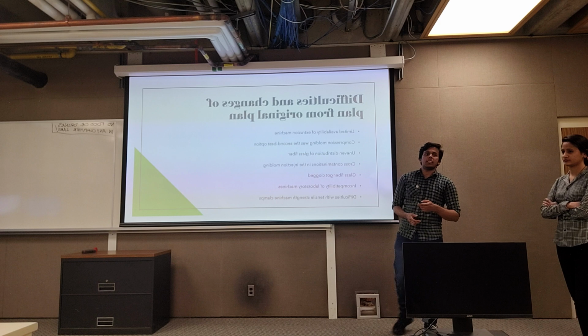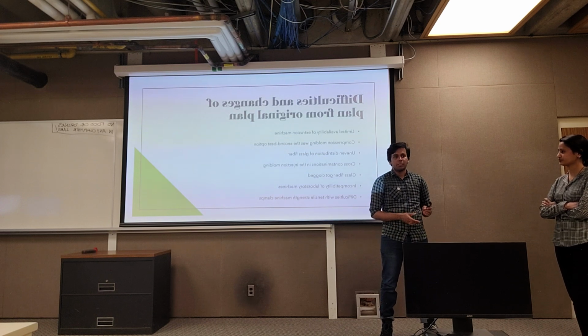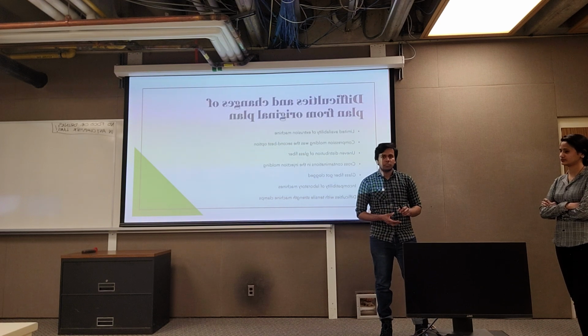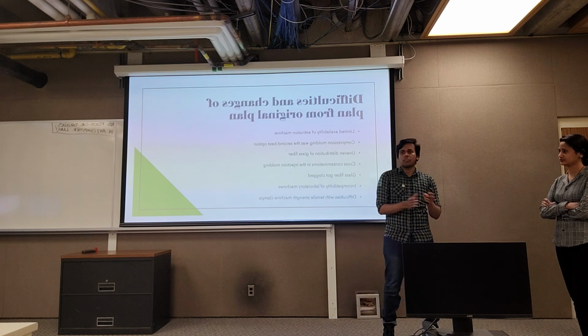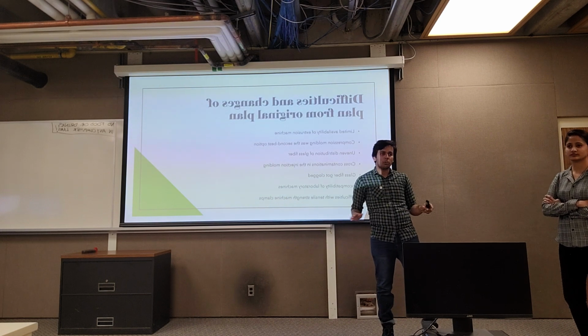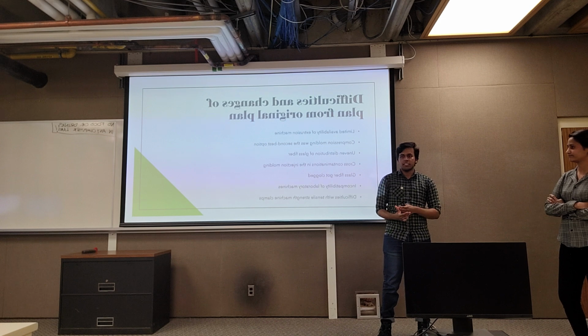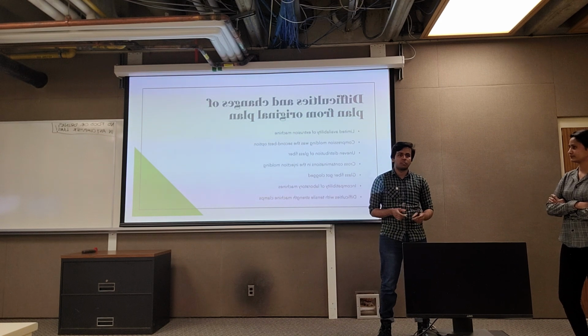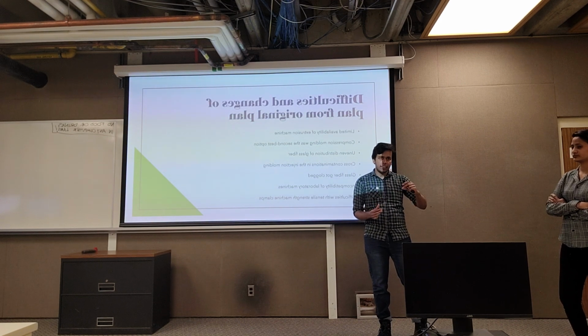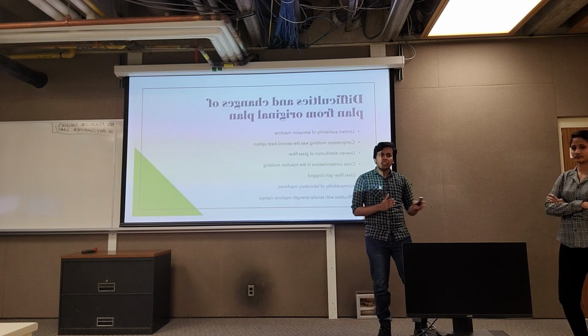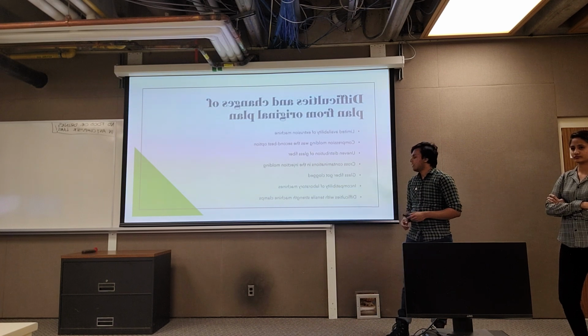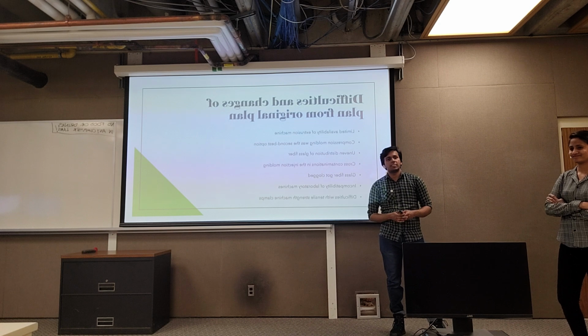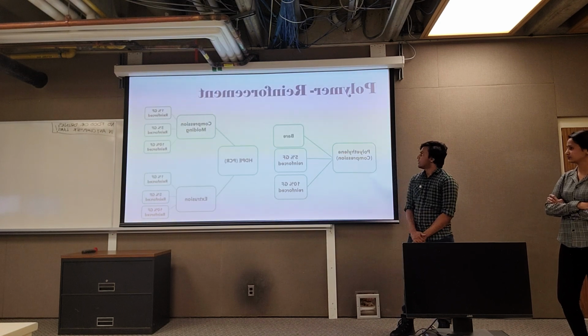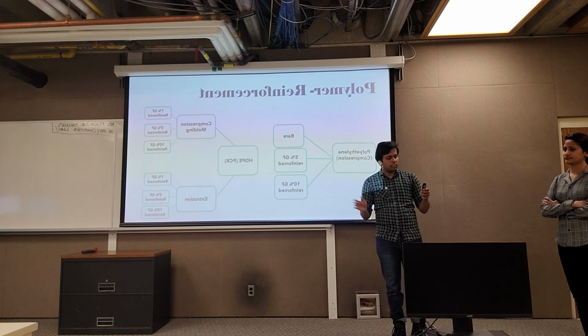Another issue was the incompatibility of the machinery. Our injection molding machine was specifically designed to create dog bone samples and only dog bone samples. But our ISO test machine was specifically designed for cylinder type samples. So there was an incompatibility issue. We also faced some difficulties with the tensile test machine because the clamps kept getting out. But we were able to overcome those problems and we created these samples.